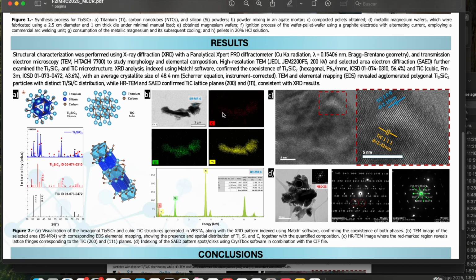The interpretation points to magnesium-driven reduction and localized thermal spikes as the drivers of phase selection. The wafer geometry supplies intimate contact, high local activity, and brief high-temperature excursions that can favor both MAX formation and competing TiC nucleation. The CO2 sweep appears to help with gas management rather than acting as an oxidant under these conditions. The advantages over conventional routes are cost, speed, and minimal infrastructure.